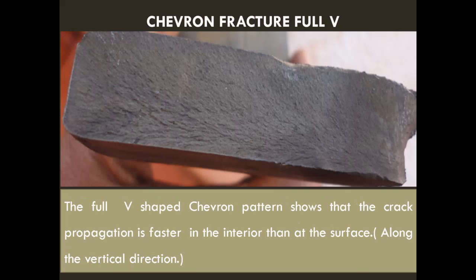This is a full-V chevron fracture. The origin of the fracture is at this corner, which is very sharp — indicating a design problem in this component. Because the corner is very sharp, the chevron fracture starts from that particular portion and then radiates outward in the form of a V-shaped fracture pattern.